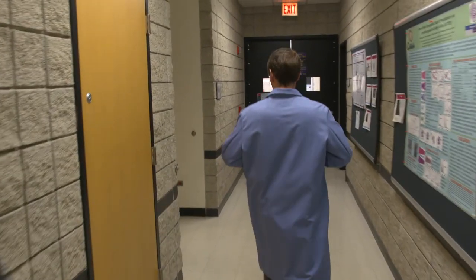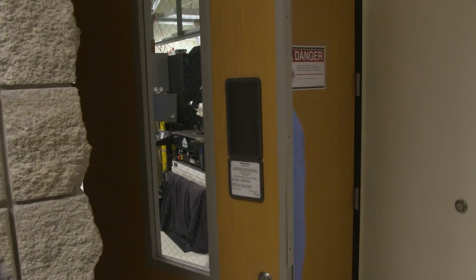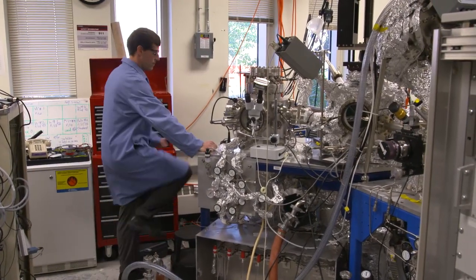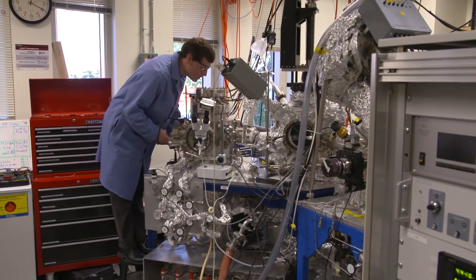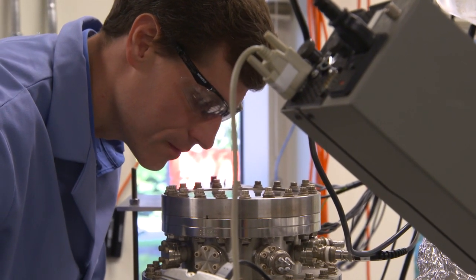And as a result, we began thinking more generally, thinking outside of the bounds of those traditional disciplines, and ultimately realized there were solutions in biochemistry that could solve a problem in the physical sciences. And so our thought was that since biochemists have utilized density gradient ultracentrifugation for similar purposes, that perhaps we could adapt that method to the carbon nanotube separation problem. And we were very happy to find that it worked.